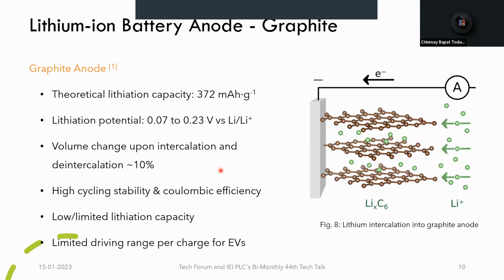Graphite has a very high cycling stability and Coulombic efficiency of more than 99%. But the driving range of electric vehicles today is limited by the moderate lithiation capacity of graphite. And therefore, it is an important need to improve the capacity of the anode in order to have a longer driving range per charge for electric vehicles.